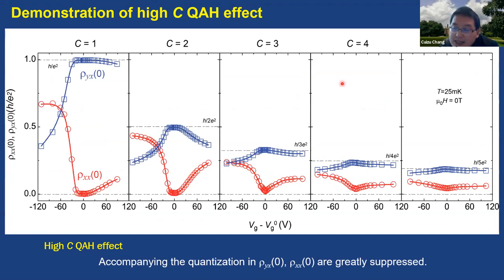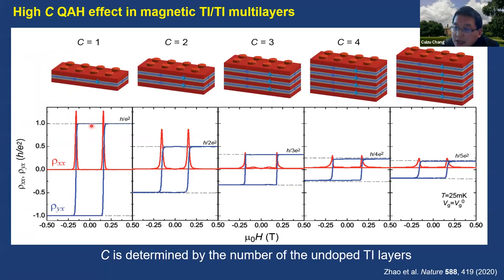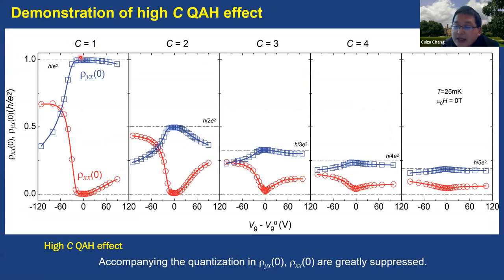And this kind of high Chern number quantum anomalous Hall insulator is further demonstrated by the gate dependence. If we just take the point at zero magnetic field and tune the gate, we can see the gate dependent zero magnetic field longitudinal resistance and Hall resistance. At the charge neutral point, the Hall resistance shows a plateau and the longitudinal resistance shows a dip. From this gate dependence data, we clearly confirm that the quantum anomalous Hall state we achieved is the high Chern number quantum anomalous Hall effect.